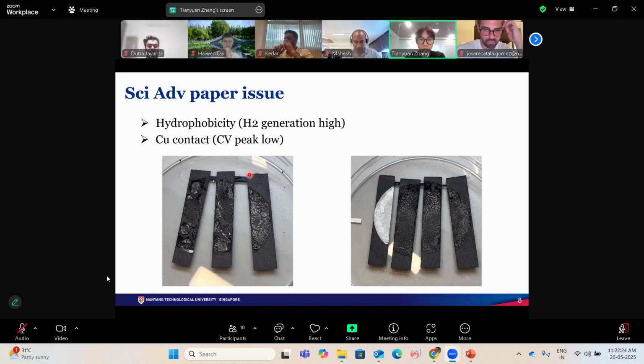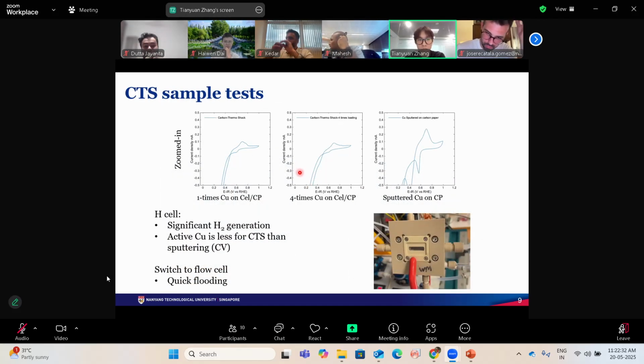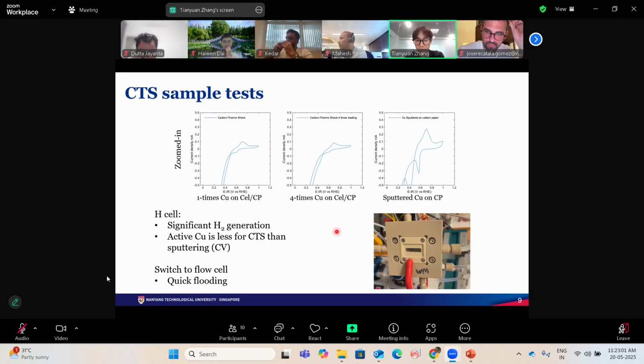And the second issue is that the copper contact will lead to a very low CV peak. As you can see, this is our CV test. No matter how many times of copper on cellulose, compared with the standard sample, the CV peak is always very low. And you can also see this video. It illustrates that our samples in the flow cell got very quick flooding, which is bad for catalysis application.